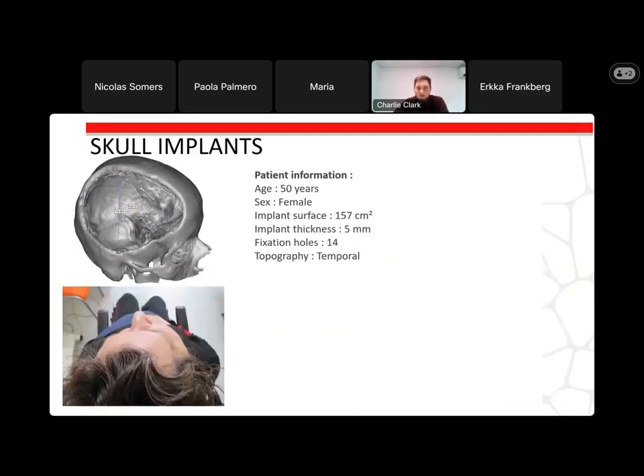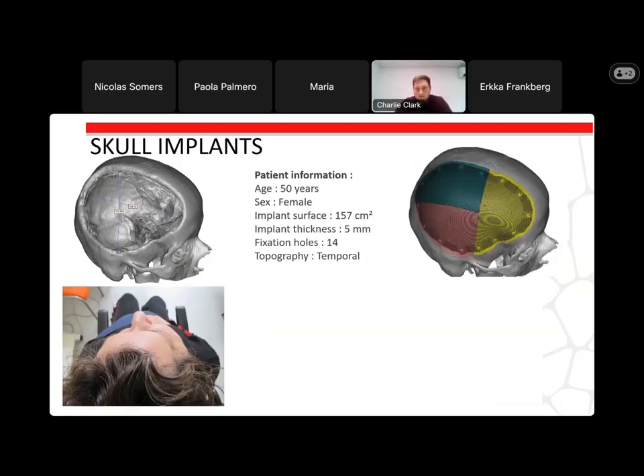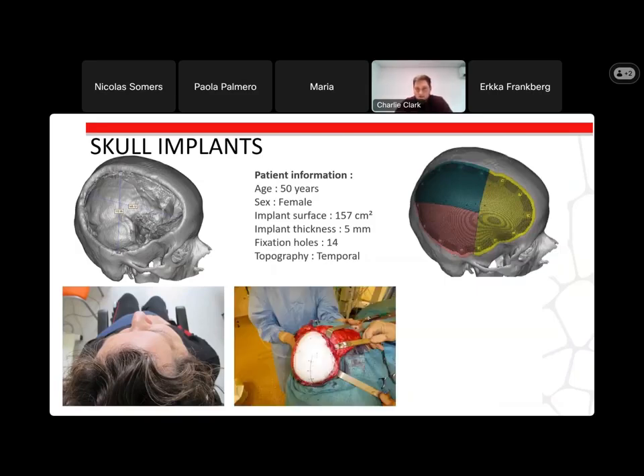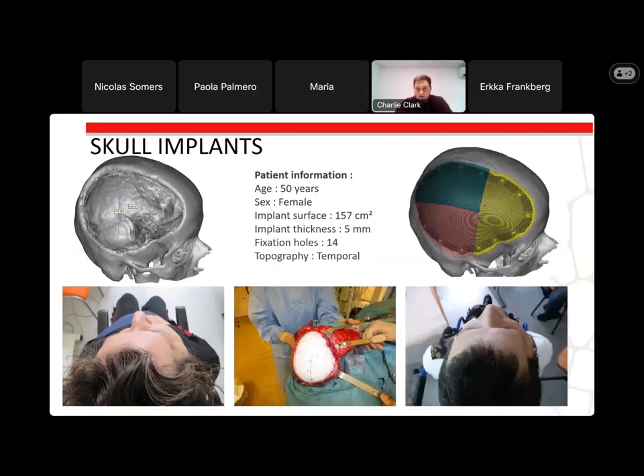This last one was also a fairly large skull implant that had to be used. So again, it had to be divided into 3 different parts for more flexibility during the surgery. So the surgery went very well, and then as you see afterwards, there were a lot better results from the study. In total, there were 15 different patients that received 3D printed skull implants that were all performed at the local surgery here.